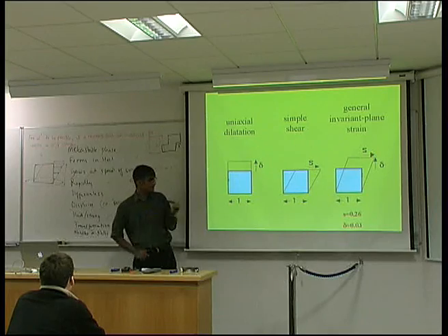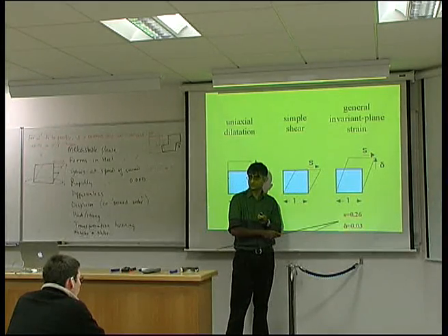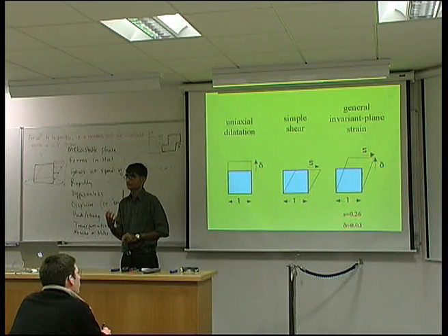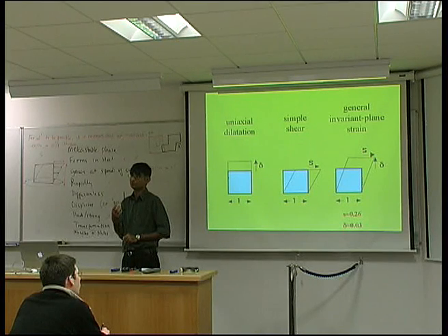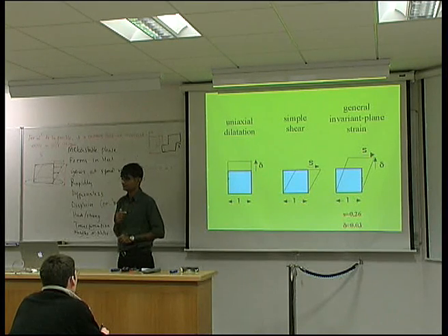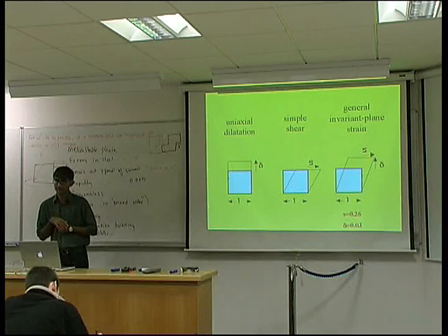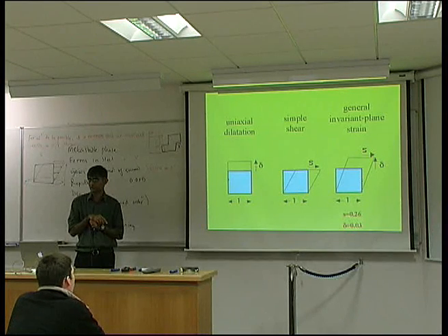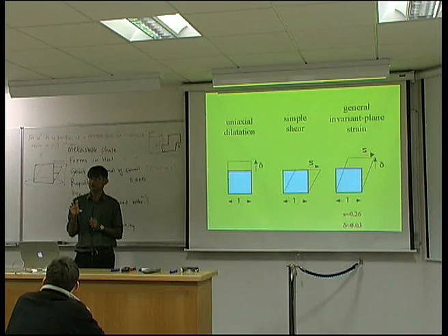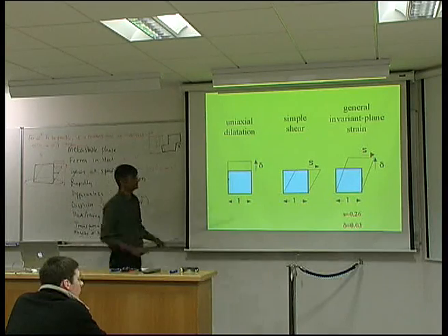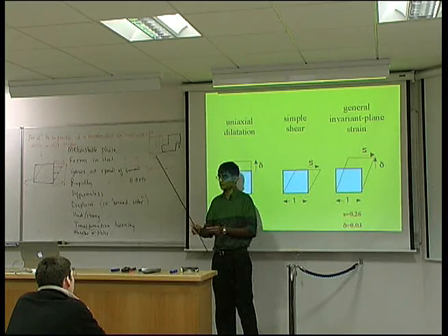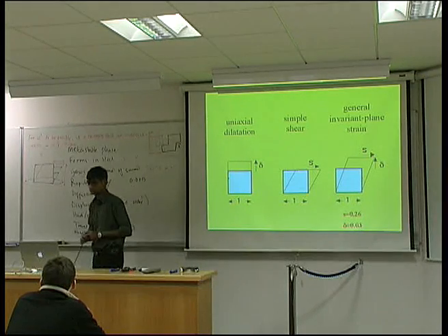Okay. Now look at the magnitudes of the strains here. This is not a percentage, this is an absolute strain. Massive deformation. So clearly this is a strain energy dominated transformation. And that's the reason why it forms as a thin plate. So when we observe the shape deformation, it is an invariant plane strain. So it's a shear and a volume expansion normal to that plane. We can measure this very accurately.